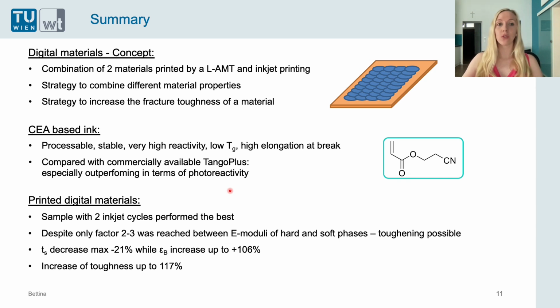And then we use the cyanoethyl acrylate-based ink to print digital materials. Here the sample with 2 inkjet cycles was performing the best, and despite the factor between the E-modulus of the hard and soft phase being only 2 to 3 instead of the 5 which was desired due to literature, toughening was possible, and the tensile strength decrease was maximum 21%, while the elongation at break increase was up to 106%, and in this way it was possible to increase the toughness of the matrix material up to 117%. So our goal was reached, the matrix material was toughened.